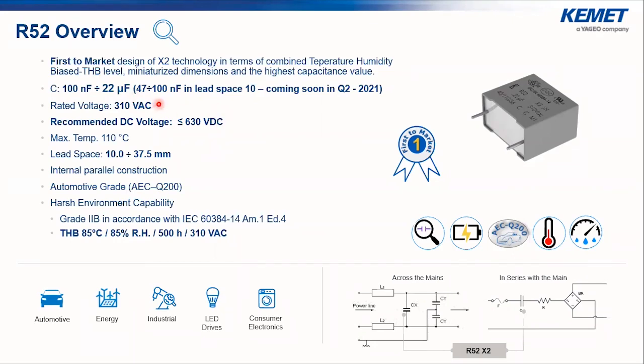We can introduce that in the second quarter of this year, we will also launch the lead space of 10 millimeters, where we will expand the capacitance range starting from 47 to 100 nanofarad in lead space 10 millimeters. Rated voltage is 310 VAC, and the recommended DC voltage for this series is also applicable, up to 630 VDC. Lead space from 10 millimeters up to 37.5.